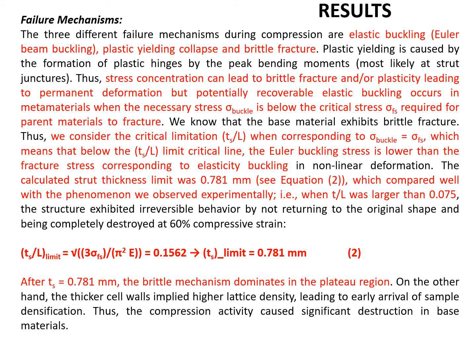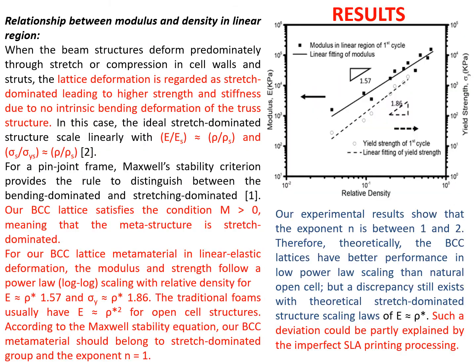We consider the critical limitation Ts over L from Euler's theory, corresponding to sigma_buckle equal to sigma_Fs, which means that below the Ts over L limit critical line, the Euler buckling stress is lower than the fracture stress, corresponding to elastic buckling. The calculated strut thickness limit was 0.781 millimeter, as calculated by equation 2. This compared well with the phenomena we observed experimentally when T over L was larger than 0.075. After T equal to 0.781 millimeter, the brittle mechanism dominates the plateau region.